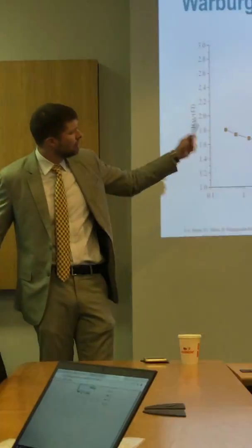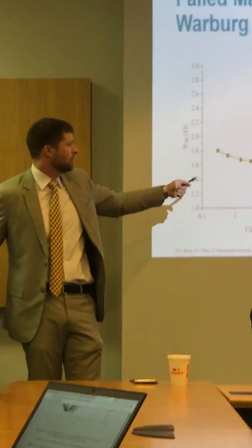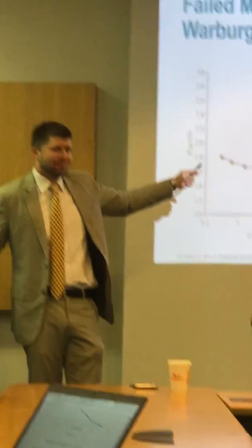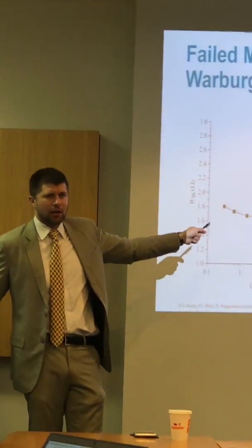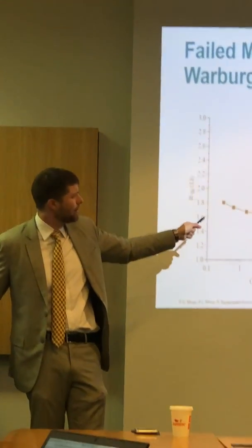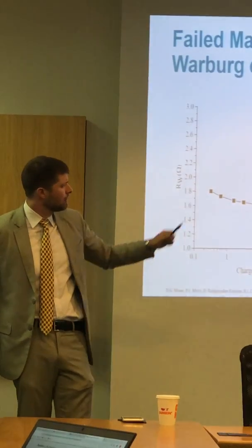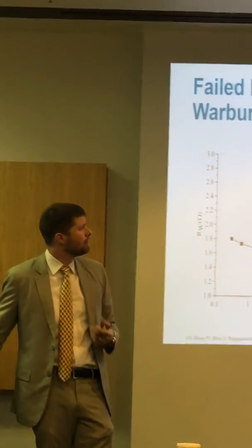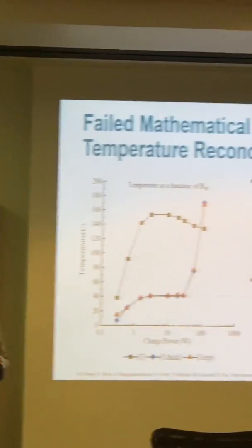And in order to eliminate this voltage error, it's quite possible if you increase the Warburg resistance an extra order of magnitude. Well, this is almost certainly not correct, because now we're 2 orders of magnitude higher than our experimental values tell us Warburg resistance should be.